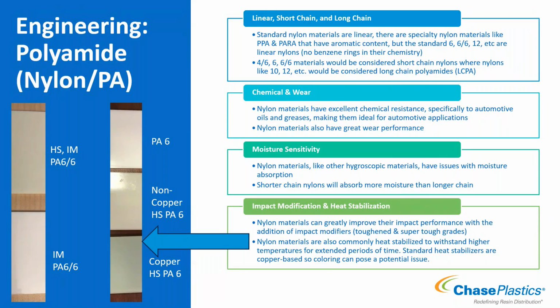Moisture sensitivity: nylons pick up moisture, so it is an issue for nylon if they pick up a ton of moisture. Like any other hygroscopic material, it can be a problem. I didn't mention it as readily, but your ABS is going to pick up moisture, your polycarbonate materials are going to pick up moisture. It just tends to be quite an issue with nylon, so I figured this was the time to bring that up.